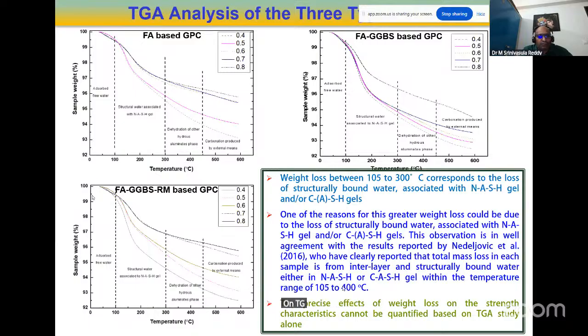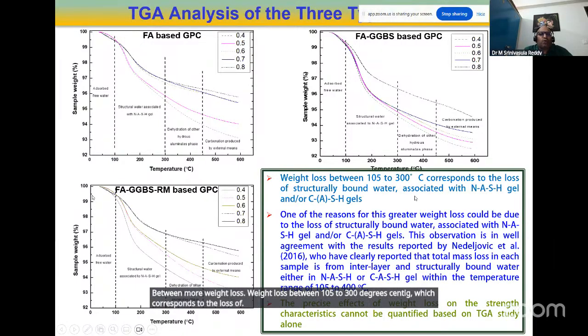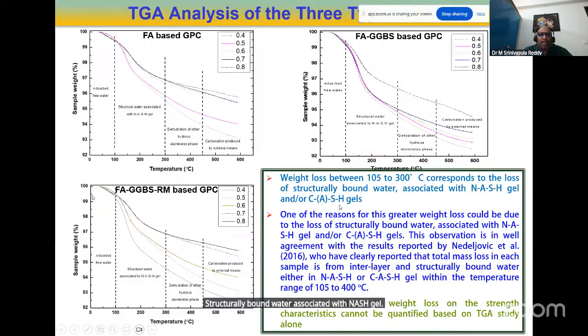And in TGA, you can notice weight loss between 105 to 300 degrees centigrade, which corresponds to the loss of structurally bound water associated with N-A-S-H gel and C-A-S-H gels. One of the reasons for this greater weight loss could be the loss of structurally bound water associated with N-A-S-H gel and C-S-H gel. This observation is in good agreement with the results reported by Nedeljkovic, who clearly reported that total mass loss in each sample is from interlayer and structurally bound water in either N-A-S-H or C-S-H gel within the temperature range of 105 to 400. The precise effects of weight loss on the strength characteristics cannot be quantified based on the TGA.